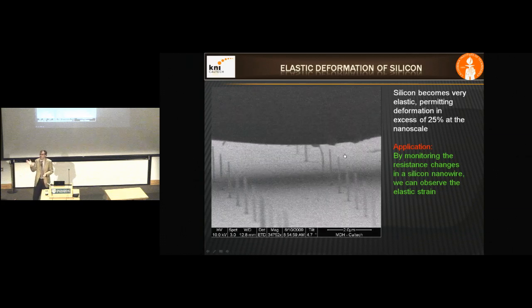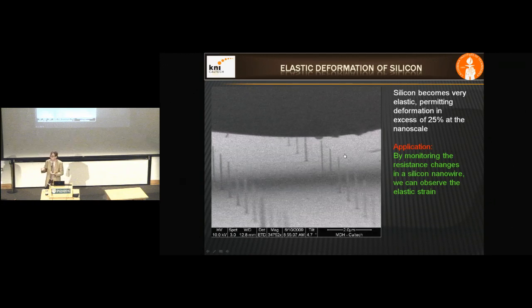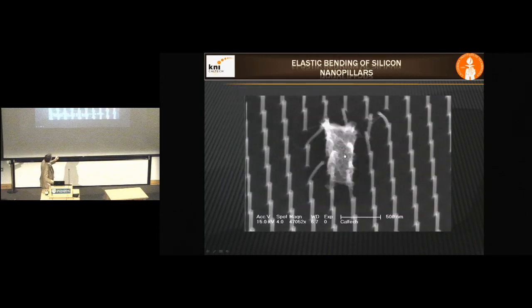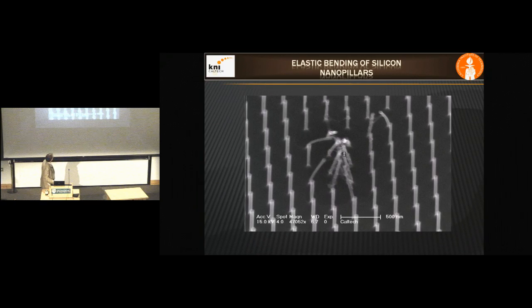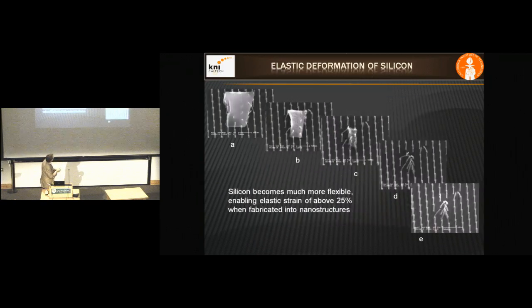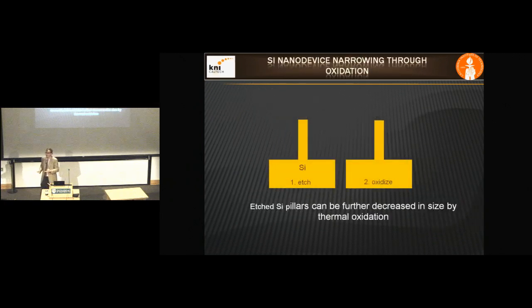The silicon bends. Normally, silicon is this really brittle material. But at this scale, you start seeing different mechanical properties. It's bending. And then when you take the probe tip off, it snaps back. In fact, if you go to the extreme case, in this kind of bending experiment, you see this little silicon whisker is almost bent perpendicular to its original orientation. And then in the next frame, it snaps back perfectly. It's 25% elastic deformation. Okay, so mechanically it's different already.